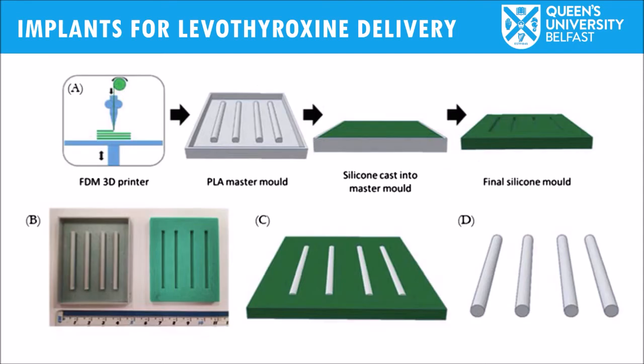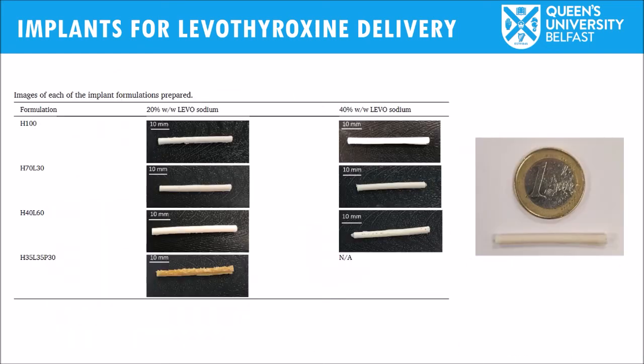I mentioned that we didn't use 3D printing for the implants themselves. We used 3D printing to create master molds, to finally create silicone molds that allow us to get our implants. For this purpose we 3D printed a master mold using PLA, polylactic acid, and later cast silicone on top of that. We use solutions containing, as I mentioned before, dichloromethane, polycaprolactone and the drug, in this case levothyroxine, to cast inside the molds and get the implant rods that are designed for subcutaneous implantation. So here you have some pictures of the different types of formulation.